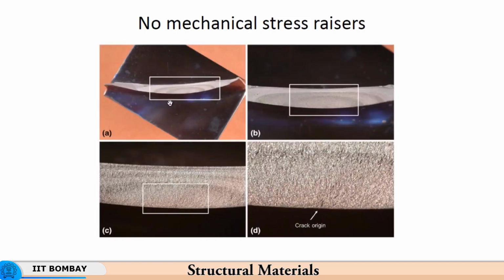But then if you look at the profile of the blade and the stress distribution and so on, if you look at the stress lines, this is where the crack originated, and apparently there is no reason why the crack should originate. So this means that in the absence of any mechanical stress raisers, which we have been talking about so much in case of ductile fracture, brittle fracture, fast fracture, fatigue, here you do not see any of these mechanical stress raisers.